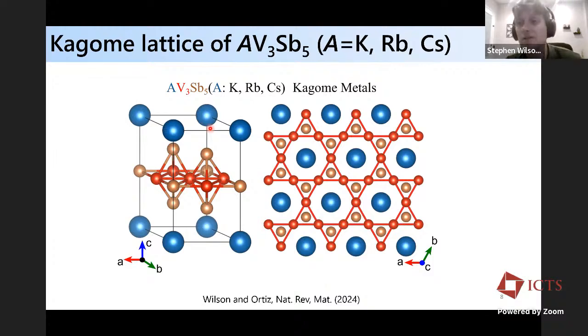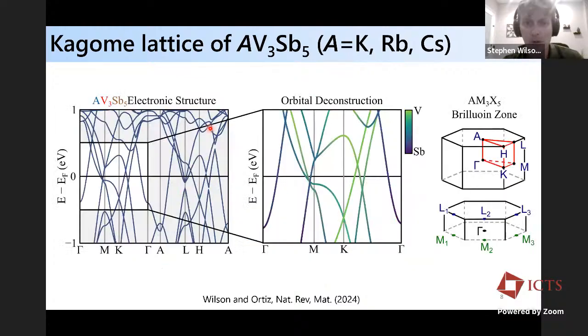This is a quasi-two-dimensional layered structure, both chemically and electronically, which can potentially heighten some of the predicted effects of nesting between Van Hove points. The interest is that these systems realize a band structure with features reminiscent of the Kagome band structure from the vanadium net. You can see a series of saddle points at the M point coming from different vanadium orbitals, and in one case mixed with an antimony orbital. The density of states at the Fermi level is dominated by these vanadium states, with the exception of this gamma pocket, which is derived from the antimony pz orbitals.